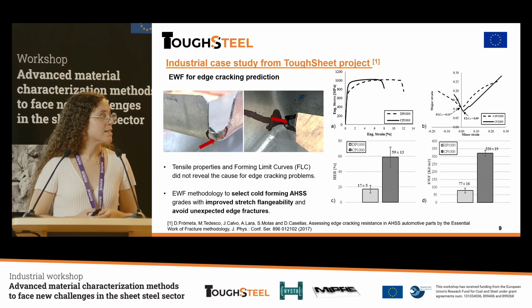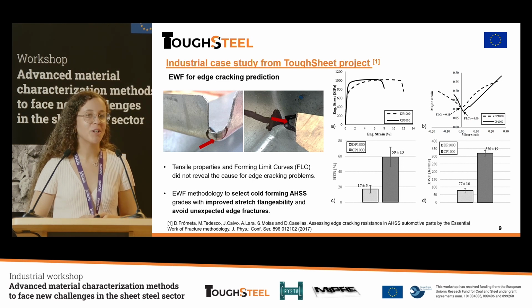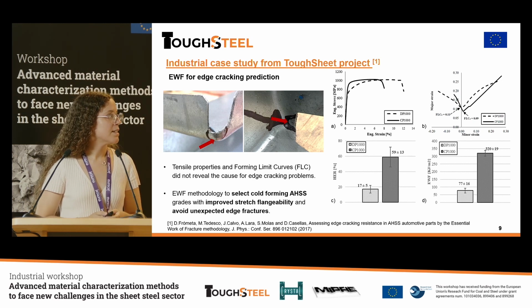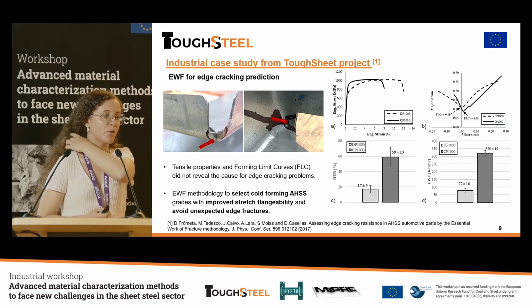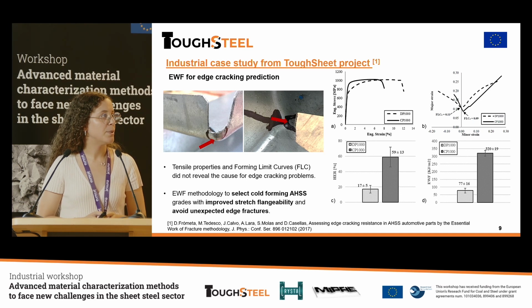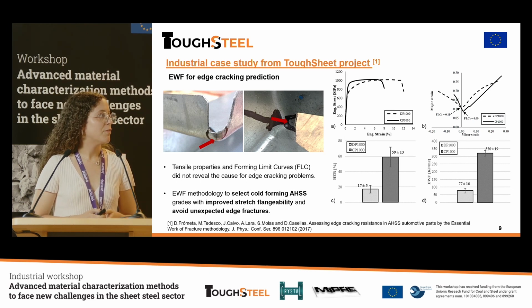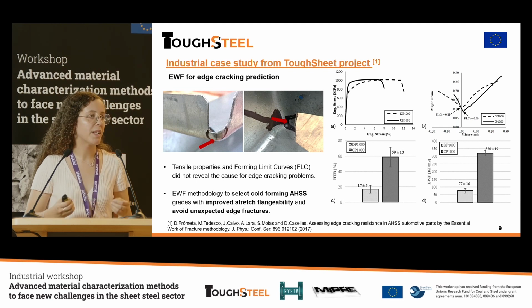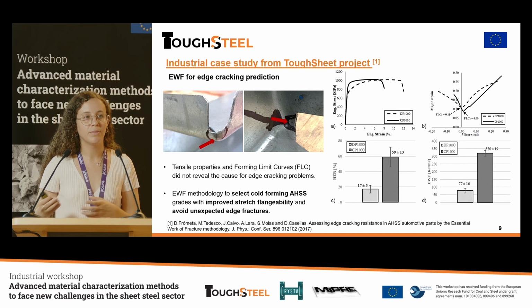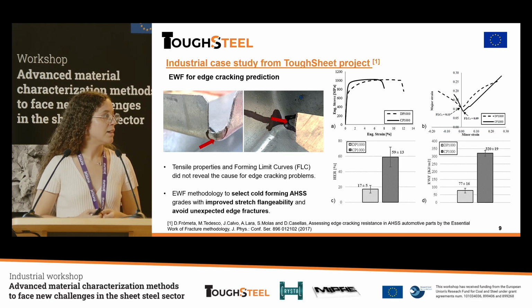The next case study we can see here was in the ToughSheet project, in collaboration with the CRF also. In this case, they were forming two materials, DP1000 and CP1000, and they found some cracks in the DP material. However, they performed the mechanical property tests and the forming limit curves, and they could not find any explanation why the DP material was presenting more cracks, because even the mechanical properties and the forming limit curves were better for this material than for the other one.